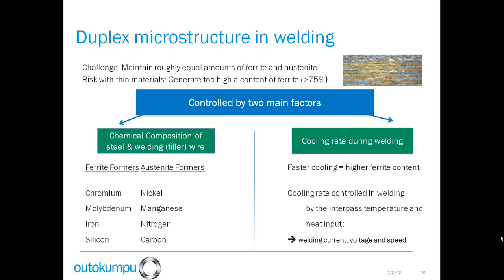The microstructure in duplex stainless steel is controlled by two main factors. It's basically chemical composition and then cooling rate during welding. And when we talk about composition, we're looking at the composition of the base metal as well as the filler metal. And then during welding, the way we control the cooling rate is through the interpass temperature that we use on multiple pass welding as well as the heat input. We need to control the welding current, voltage, and speed. Those are all the inputs for the heat input.